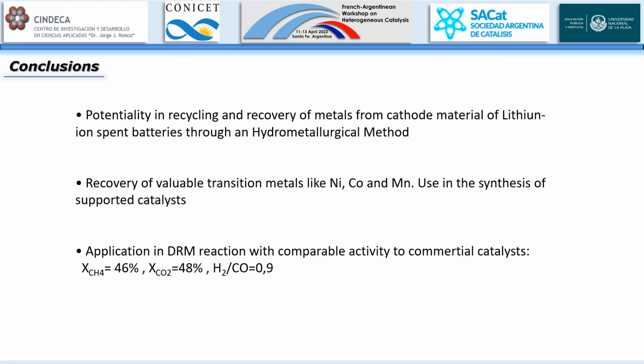In conclusion, it's possible to use chemical recycling for the recovery of important and high-cost metals such as nickel and cobalt from spent lithium-ion batteries, and use these metals in the synthesis of solid catalysts that have potential application in industrial reactions, such as the dry reforming of methane. The performance and conversions of the catalysts were comparable to the commercial ones and gave a hydrogen to carbon monoxide ratio near unity.